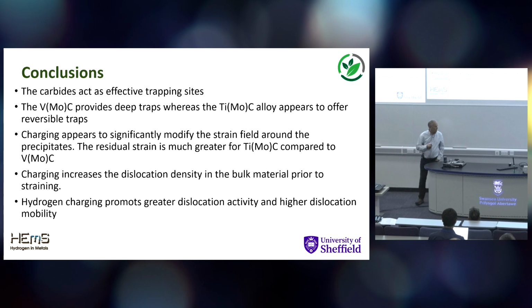So to conclude, the carbides are very effective at trapping sites, but we clearly had a very different behavior between the titanium carbide and the vanadium carbide. It would appear that the vanadium carbide gives you an irreversible trap, so the hydrogen is quite safe. But in the case of the titanium carbide, it is a reversible trap, so the hydrogen just comes out under the applied stress and can do much more damage.